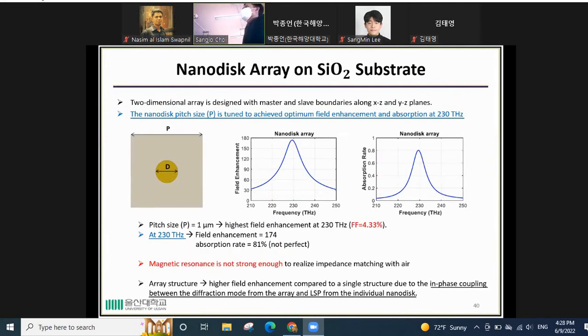So after getting parameters from the single nanodisk, we then move to the nanodisk array on the silicon dioxide substrate. From the array, we also tune the nanodisk pitch size, which is the distance between the center of a nanodisk and other nanodisks in the array, to achieve optimum field enhancement and absorption rate at 230 terahertz. And this is the field enhancement and absorption rate for the maximum pitch size, which is 1 micrometer.